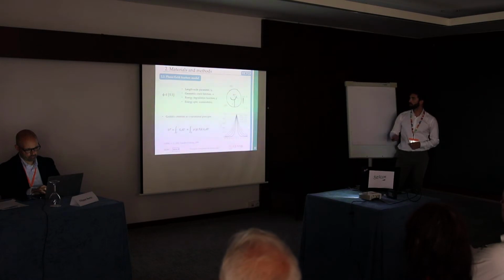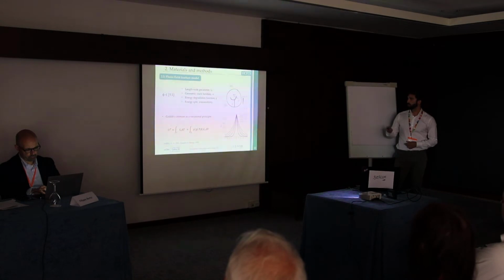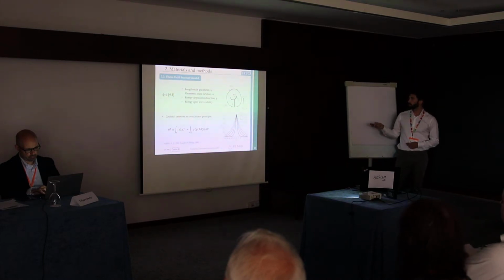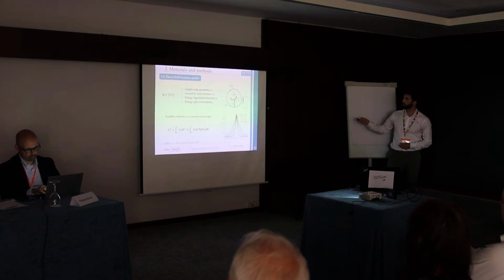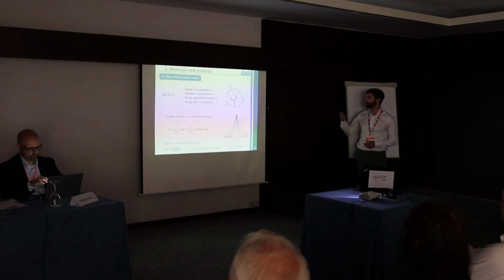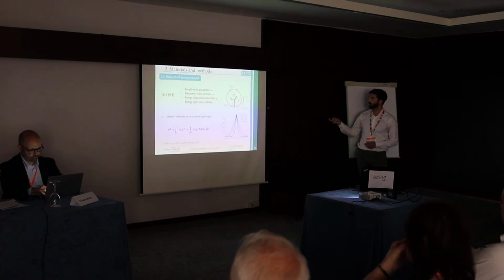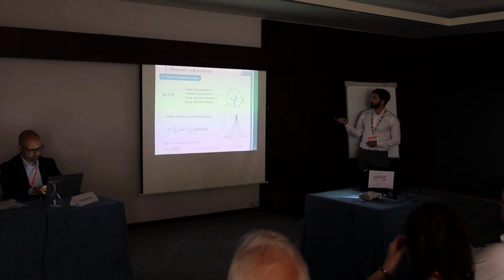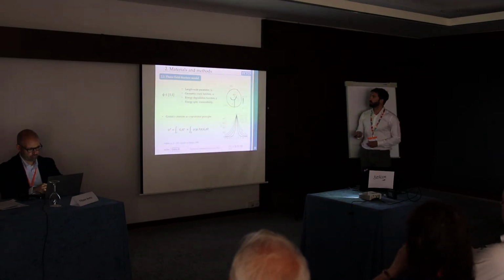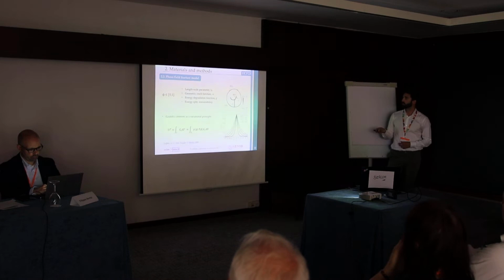We have here on the figure on the right an example of a general body, 2D in this case, but it could be in 3D, of a diffuse crack, because this variable defines the crack in a diffuse way, going from 0 to 1, and we can see here how the material is losing its strength till the crack phase on the black line. What happened with this line in red? This is the phase field profile, and it defines the evolution or the distribution of this parameter along this perpendicular.